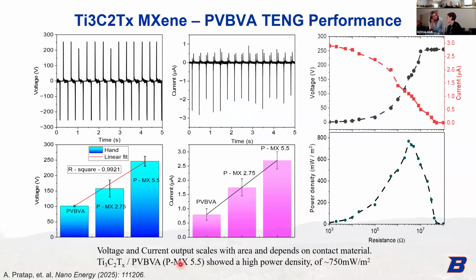So here's some of the TENG performance versus concentration of the MXenes. We were able to get up to about 5.5 weight percent of MXene in the PVBVA before they crashed out. That's the solubility limit, and the voltage that we're able to achieve with the addition of the MXenes is about 200.